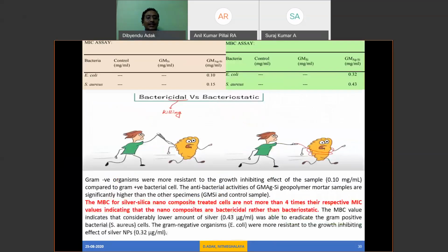Next, the MIC and MBC values are very much needed for this antibacterial study. In the MIC value, for the E. coli gram negative bacteria, the MIC value is 0.1 and the other value is 0.15. Similarly, the MBC value is there. From this MIC and MBC value, we can say that if you add 0.1 milligram per liter of the silver silica geopolymer mortar to the bacterial stock, it can stop their growth. Similarly, if you add 0.32 milligram per liter, they will kill all the E. coli bacteria.